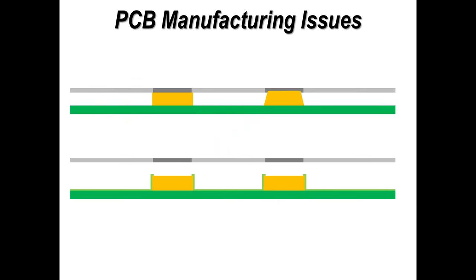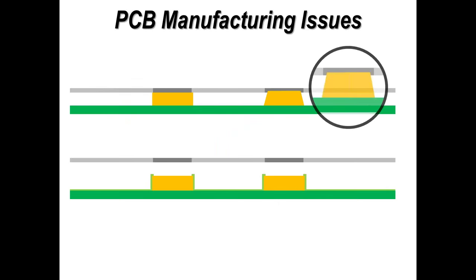Now, in this example here, I just show you what can happen if the pad size is significantly smaller. And what tends to happen here is the pad goes into the aperture of the stencil, and it will affect the volume of solder paste or conductive adhesive which is present on the pad as it releases. And certainly it will tend to give you poorer print definition. And this close-up just shows you that. So again, looking and actually doing some measurements on the printed circuit board, don't always believe the pad is the size you've designed. It generally will never be. So understand what impact the pad size can have on your printing process.